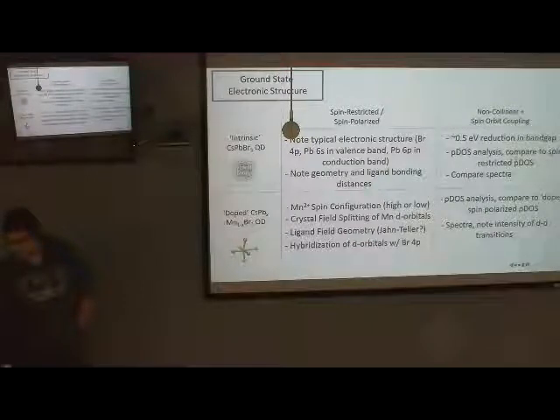So it would be interesting just to compare the orbital analysis for HOMO and LUMO for both systems. And also compare spectra, because there could be changes in oscillator strengths too if there are changes in the orbitals for all the states. And then for the doped system with non-collinear and spin orbit coupling, same thing: PDOS analysis, seeing how the orbitals change with the inclusion of spin orbit, and spectra. Then we're able to see d-d transitions or spin flip transitions from the metal dopant, and note the intensity of it, because it's there, but it's very, very small.